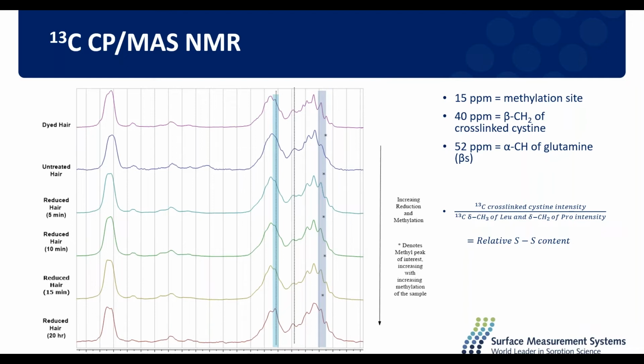This peak here at 52 ppm is the alpha carbon of glutamine, and this is glutamine in its beta sheet form. We can see really nicely from that untreated sample that the peak increases upon dyeing and also increases on reduction, especially for this 20 hours reduced hair sample. And that's really showing us that we're introducing some disorder through damage. We're increasing the beta sheet content of keratin in our hair samples.